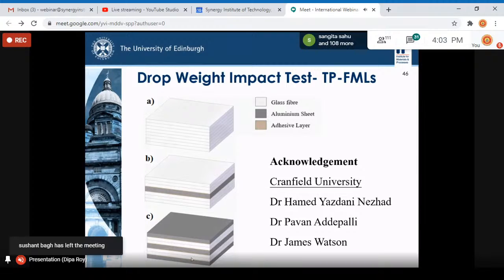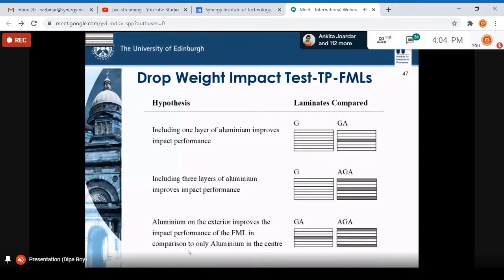We manufactured different laminates with different positions of the aluminum alloys. This was again done by a master student, in collaboration with Cranfield, with Dr. Hamid, Dr. Pavan and Dr. James Watson, who were very helpful in the collaboration activity. Three different types of laminates were manufactured. The first one was an all glass fiber composite. The second one had an aluminum alloy layer in the mid plane, and the third had three aluminum layers. The main objective was to compare the energy absorbing ability of these laminates: a pure glass fiber composite versus the composite having one aluminum layer and three aluminum layers, as well as a comparison between one layer and three layers of aluminum.